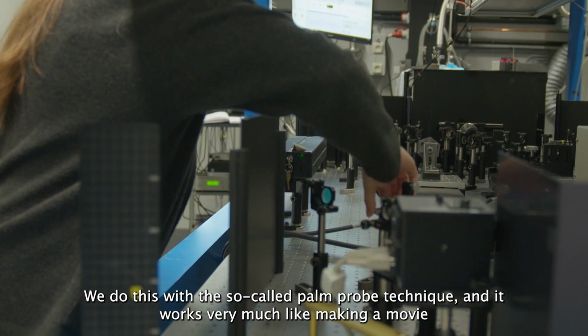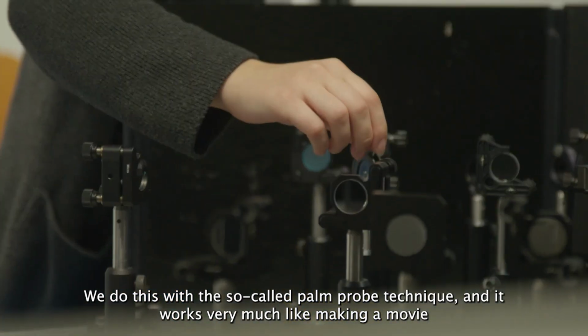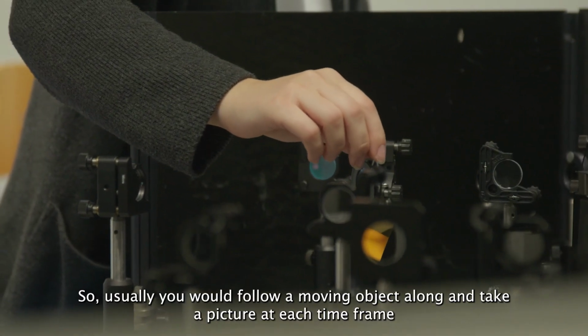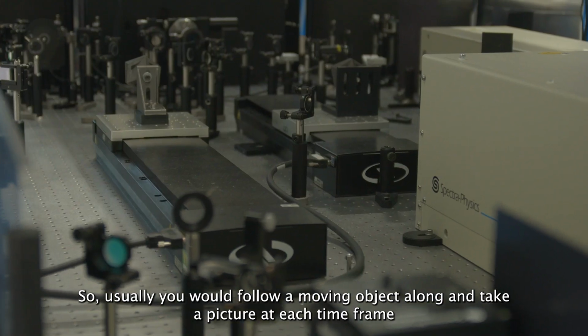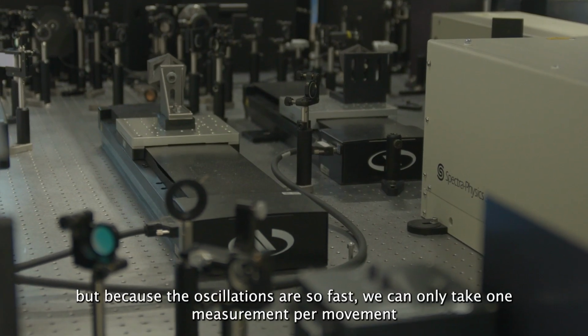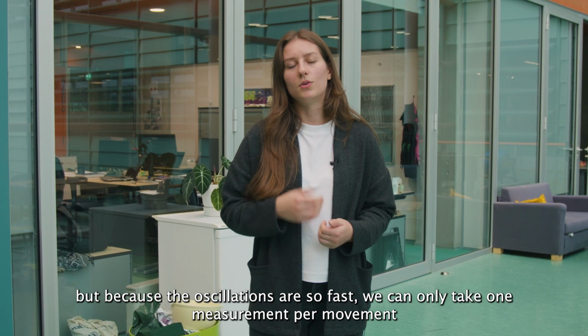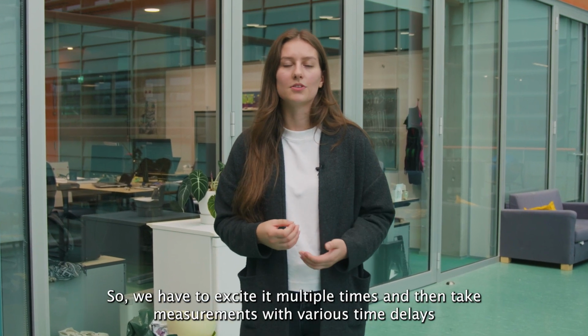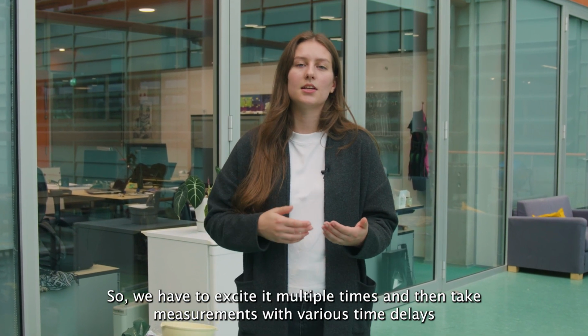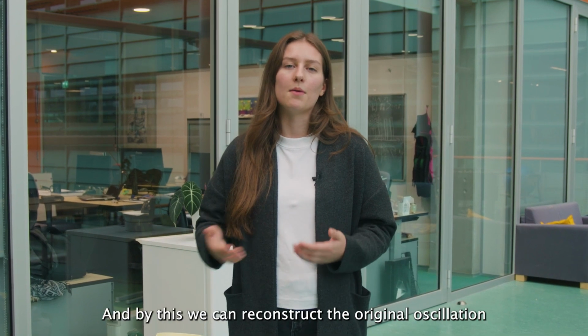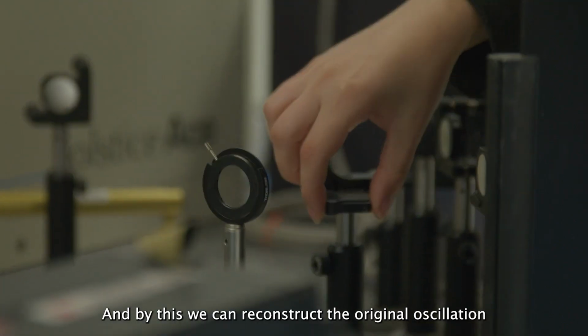We do this with the so-called pump probe technique, and it works very much like making a movie. Usually you would follow a moving object along and take a picture at each time frame. But because the oscillations are so fast, we can only take one measurement per movement. So we have to excite it multiple times and then take measurements with various time delays. By this we can reconstruct the original oscillation.